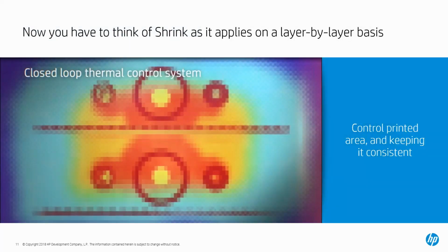When we move into MultiJet Fusion, as we said, we use infrared energy to fuse the parts together. One of the parts of the system is a closed-loop thermal control camera, which is based on the top of the machine, which reads the temperatures across the bed. And this allows us to see where hot spots and cold spots are of the parts that are being printed, and allows the machine to adjust the bed temperature as it prints throughout the build.